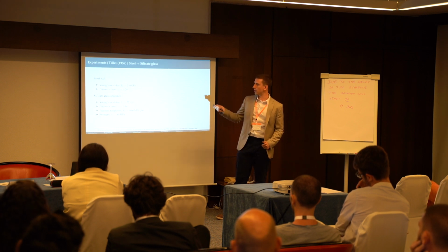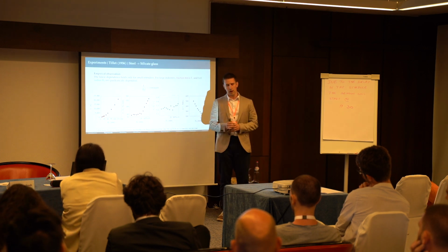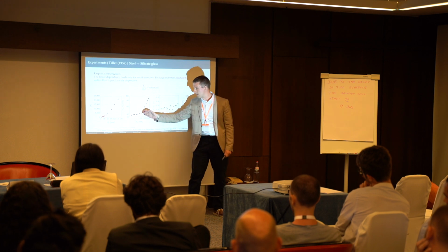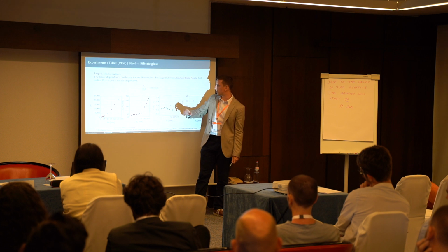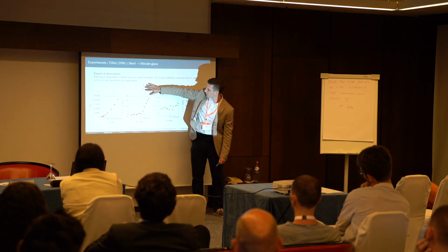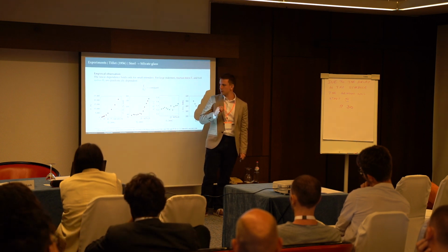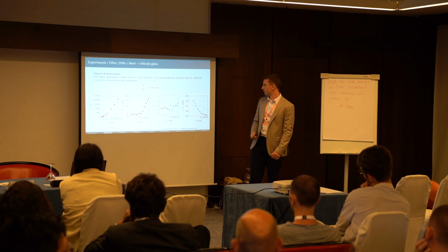And 50 years later, Tillet did experiments with bigger balls and noticed that this region of linear dependence ends at a certain ball size, and with bigger balls, the regime completely changes. And this dependence on the square of the ball radius starts to make sense. But how to explain it?